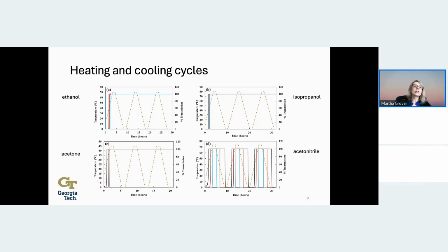So at the point where we reach 100, we can note that time. Visually, we can come straight down vertically and see what the temperature was at that time. That gives us the solubility temperature associated with that concentration, which we know from the amount of material that we initially added, and that is fully dissolved. So that's how we get the solubility here. We determine that we're fully dissolved, continue to heat higher, hold it for some time, and then begin to cool. What we see in the ethanol is no crystallization over that time frame.